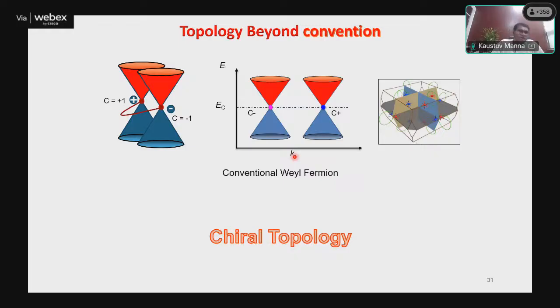So if you want a physical property coming out of the Berry curvature, and you want to isolate the response of one Weyl point compared to the other, there is the CPG, the circular photogalvanic effect. There is one effect I will not have time to cover. Like an optical response, you put circularly polarized light on a material, and the DC current it generates is proportional to the Chern number of your Weyl point. So if you have two Weyl points active, depending on the energy, if this Weyl point is active, then this Weyl point is also active because it's at the same energy, right? If there is a DC current from plus C, then there will be an opposite DC current from minus C. So if you take a conventional material and do such an experiment with circularly polarized light, you will not get any net DC current, because whatever plus DC current comes out from one Weyl point, it simply nullifies the other.